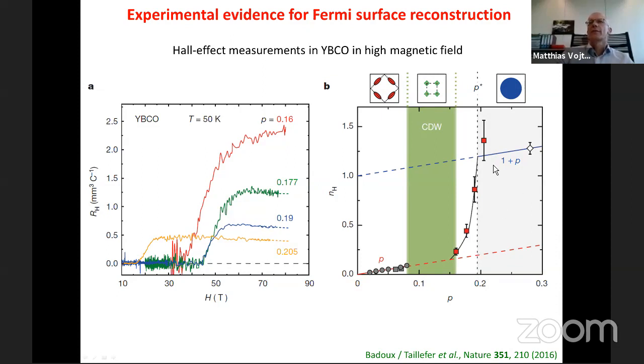And what you see is that this carrier concentration in the overdoped regime is actually given by 1 plus P. And P here is now the deviation from half filling. So 1 plus P is the correct number of electrons. So this here is a metallic state which fulfills Luttinger's theorem. But here on the low doping side, there are various data points which are on a line where the carrier concentration is P. So this violates Luttinger's theorem.